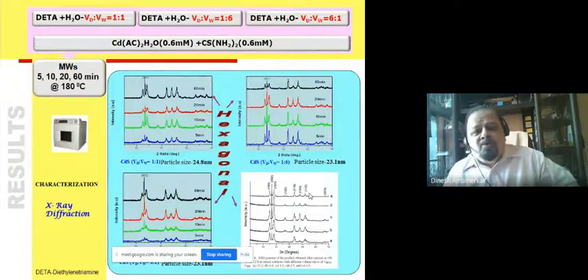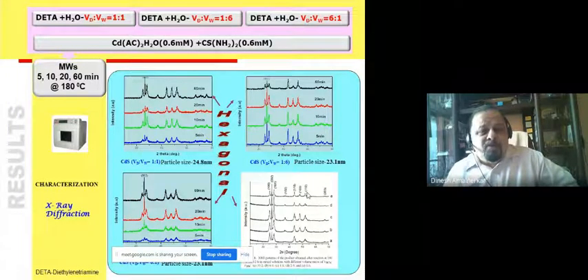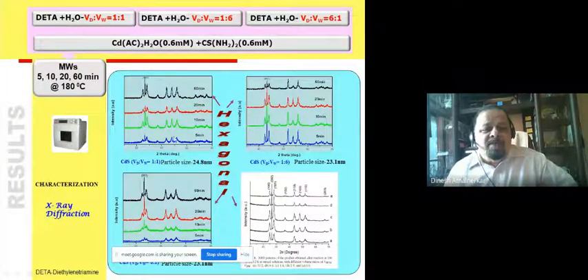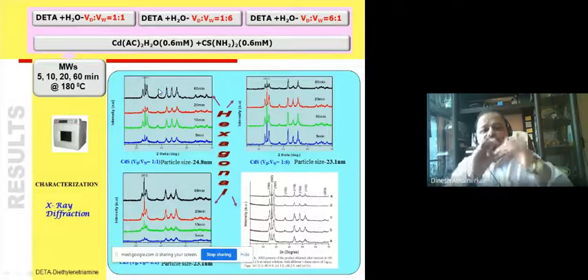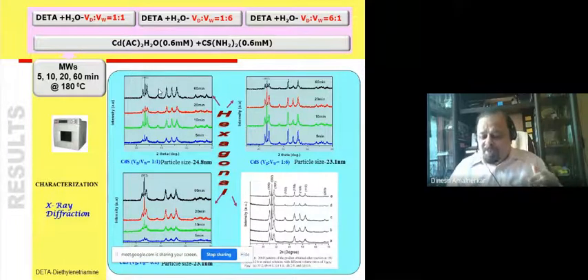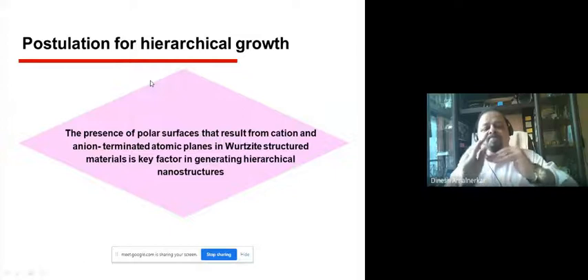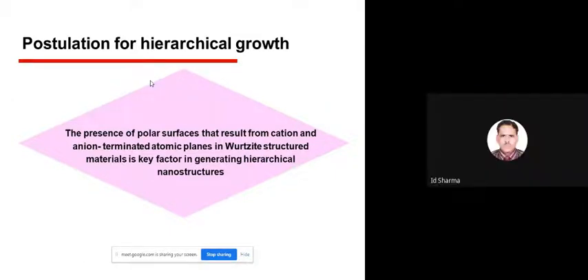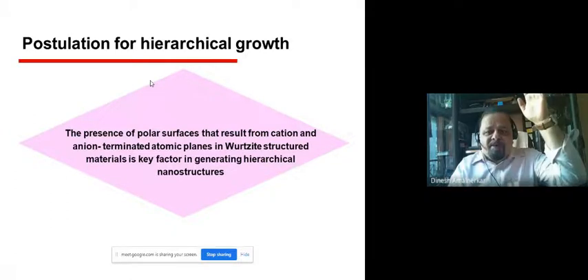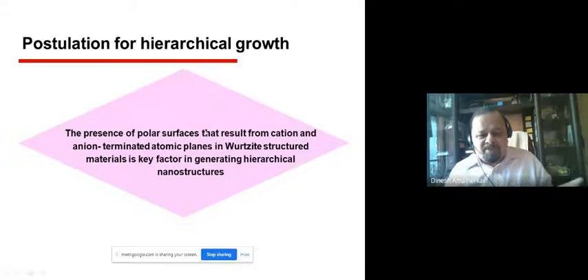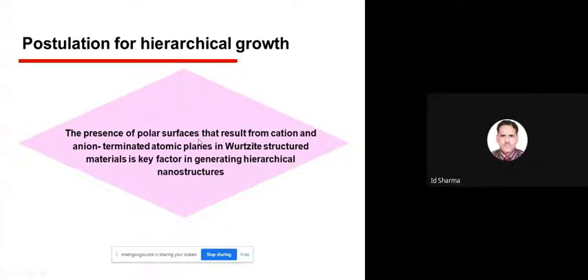Then we wanted to know why we are getting the hierarchical nanostructures all the time in this kind of semi-solvothermal route under the microwave condition. We very carefully studied our X-ray diffractogram, and we noticed that this is not just a hexagonal structure. It is the hexagonal structure of cadmium sulfide with 002. Everywhere we have seen 002, that is the basal plane orientation. This 002 plane is such that it contains either cadmium ions or sulfur ions. So these are called polar surfaces. When the plane which contains just cadmium comes in contact with sulfur, there is a hierarchical buildup, a one-dimensional buildup. That is what is said here. The presence of polar surfaces, as I said, contains either cadmium or sulfur.